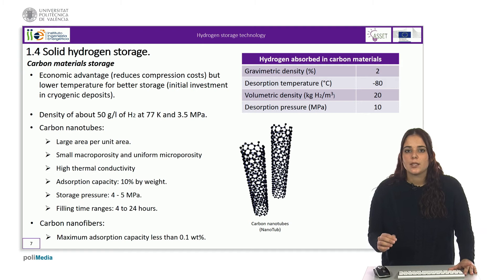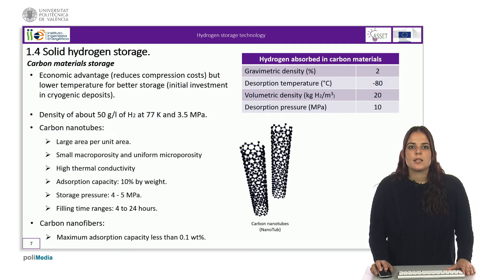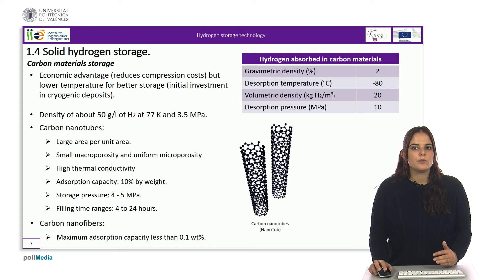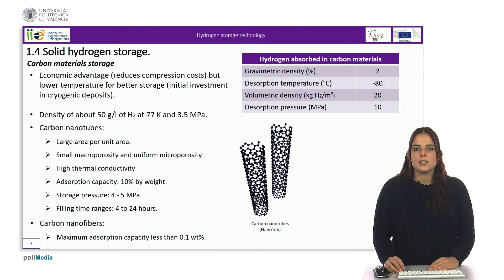The second option for solid storage is storage by carbon materials. Conveniently treated active carbon can be used to store hydrogen with a density of about 50 grams per liter of hydrogen at 77 degrees Kelvin and 3.5 Megapascals. The storage by absorption in active carbon has the same advantages as compression storage: for a given equivalent density value, absorption requires a lower pressure, and at the same equivalent pressure, more gas is stored. Therefore, it has a great economic advantage as it reduces the cost of compression. However, for better storage, it may be necessary to lower the temperature, involving an initial investment in a cryogenic deposit.